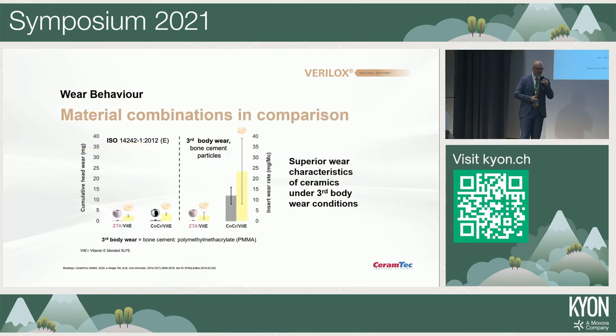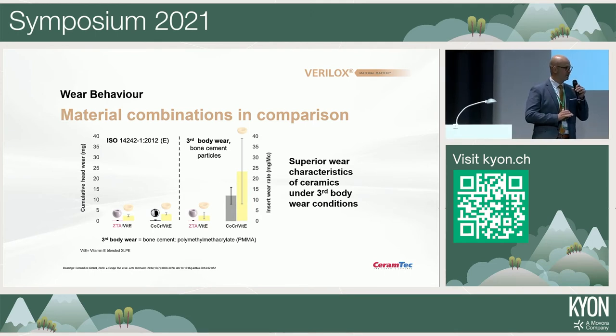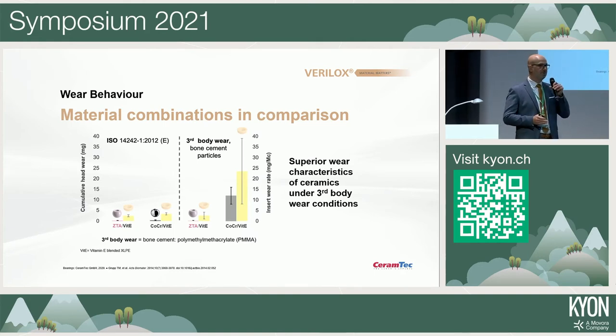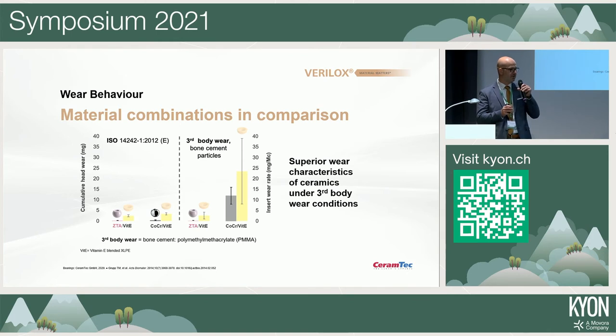And that can you see in the wear testing, and this is a wear test from human hip implants where we test the ceramic in comparison to metal heads with the combination of polyethylene, which is a polymer. And there you see, even under the ideal situation, that's the left-hand side, when you simply apply the standard gait cycle without any disturbances, like third bodies which can make scratches, you see a smaller debris of the poly component and nearly no debris of the ceramic component. And if you apply so-called third bodies, which could be small particles of cement or small particles of an HA coating, which you always will lose during the application of a press-fit implant, then the wear debris in the metal and poly combination is much higher than in ceramic and poly. And the reason for this is the scratch resistance of the ceramic material.